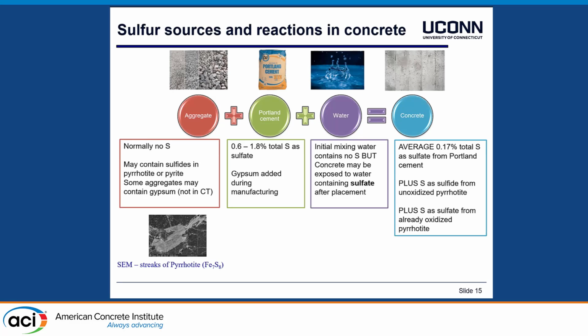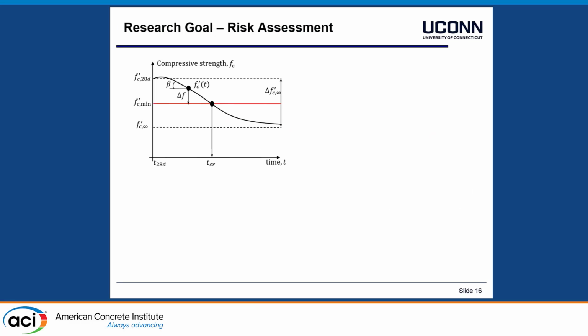So on average, if you take a general mixing proportion of concrete for foundations, with Portland type 1 cement being used and the gypsum content between, let's say, 2.5% to 3%, with all of those assumptions you make a calculation. It's about an average, and it's not varying, of course, 0.17% in total sulfur as sulfate from Portland cement. So this is kind of your baseline you have in the concrete. And then you have sulfides from unoxidized pyrrhotite, and then you also have a sulfur source from oxidized pyrrhotite, which is then in the form of sulfate already in the mix, or further reacted to form ettringite.